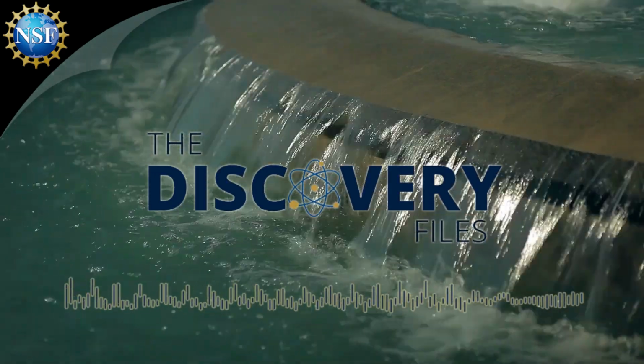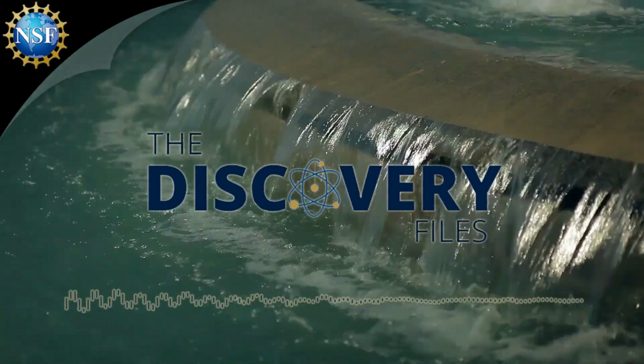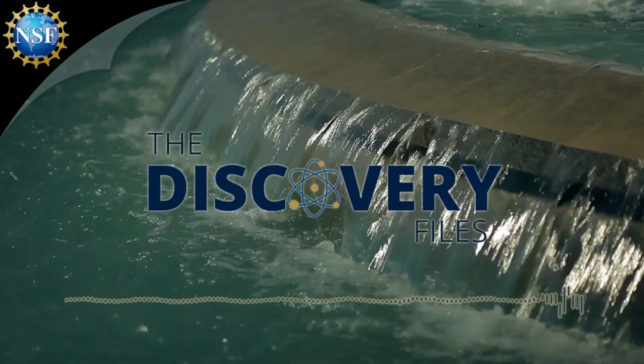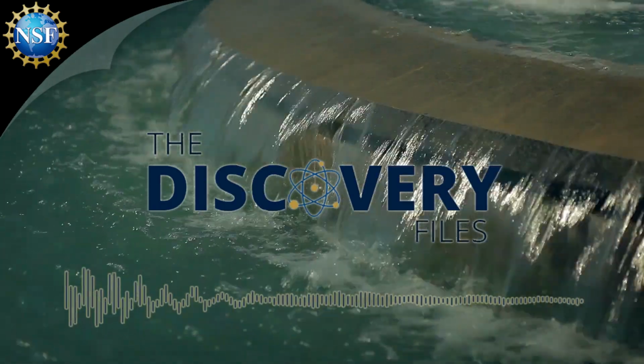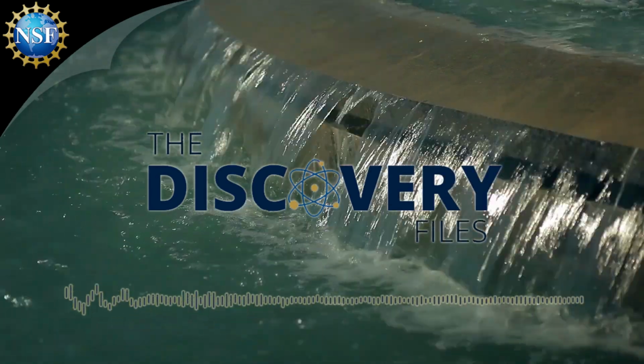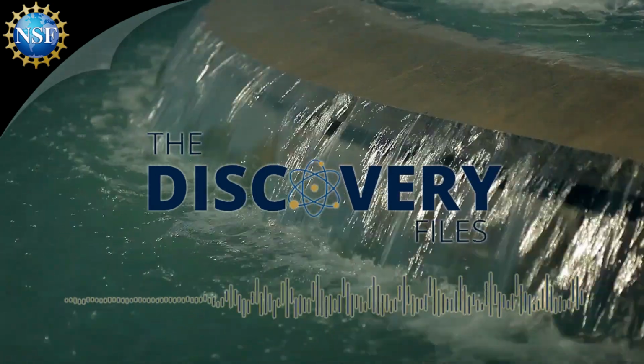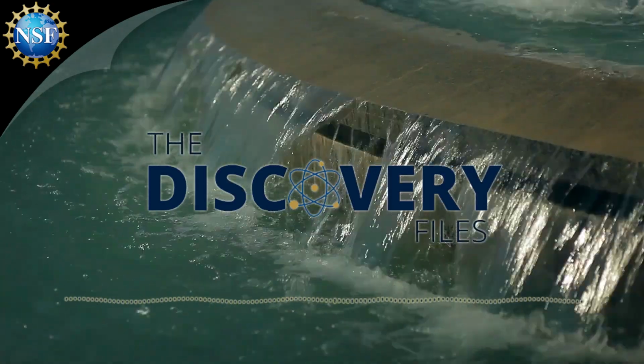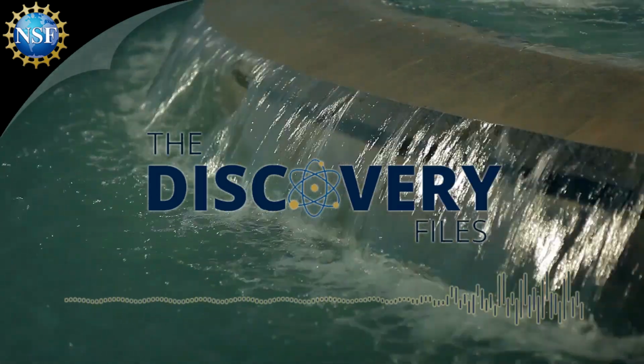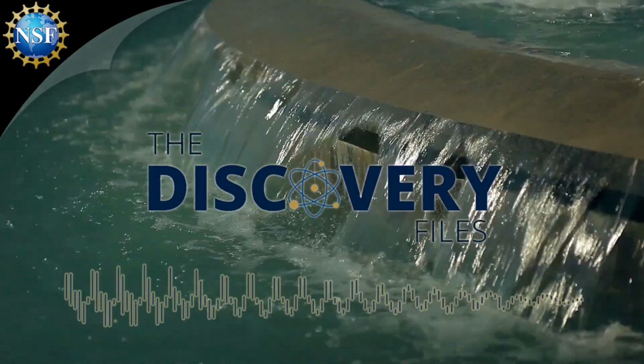And in our structure, we made a hierarchically organized multi-scale porous structure that is made of interconnected graphene and carbon fiber. This structure more effectively acts as a trap to absorb ionic impurities and nano- and microplastics on the large surface of the graphene and carbon fiber. These properties make the surface area of this structure larger than activated carbon. And for the pore size, we have double porosity: nanopores that come from the defects of the graphene and carbon fiber, and macropore structures that come from the interconnected structure. And this makes the graphene and carbon fiber aerogel structure different from activated carbon, and more effective because of these properties.